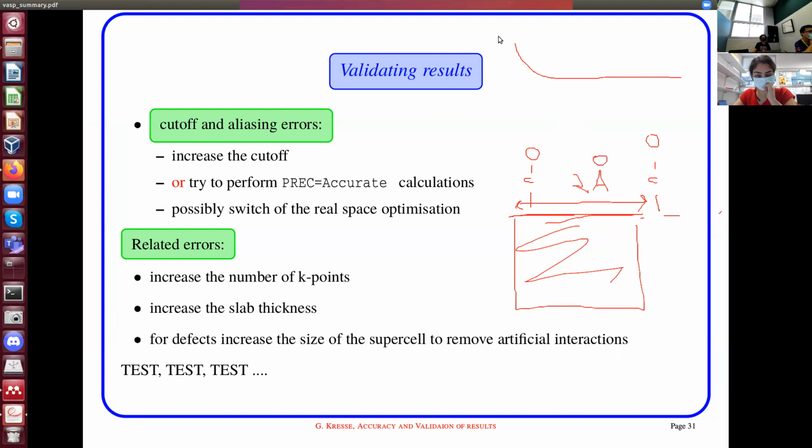You need to think, let's say, if this is a graph of repulsion versus distance, of course, there is a threshold value where your repulsion goes to 0. And usually this one is 8 to 10. That is already good enough. If you want to have the best simulation ever, you can also just have a supercell of 100 angstrom, and then you for sure will not have any interaction, but it will also take months to converge.